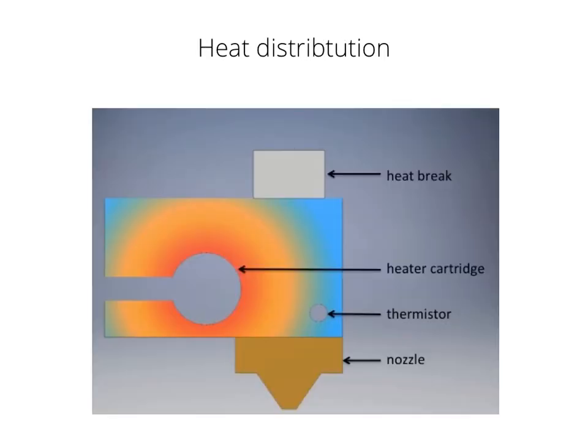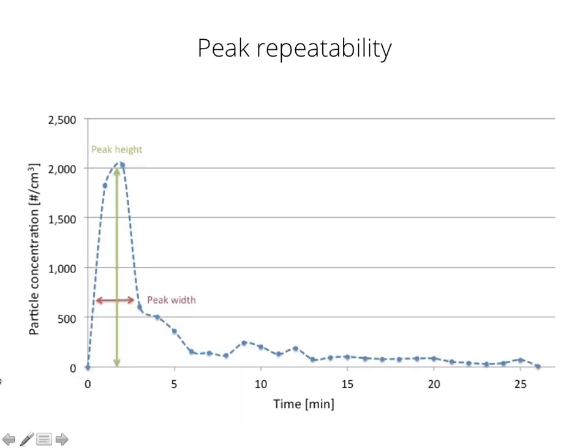Also, one interesting factor is the heat distribution can maintain itself for longer than 20 minutes, meaning after the extrusion process itself was finished and the hot end started cooling down, after 20 minutes the thermistor told me, oh well, we have cooled down to ambient air temperature, and I wanted to repeat the process itself. The peak itself was not repeatable anymore, so the peak was a lot smaller, and then we reach a steady state a lot faster.